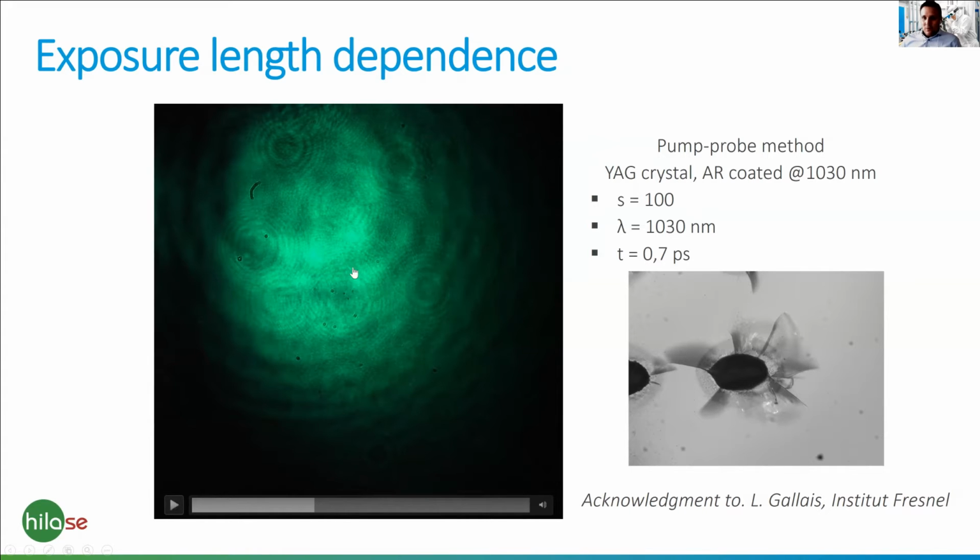At a certain moment, the system of electron recombination and excitation over and over again, releasing the energy into the lattice, eventually leads to the creation of damage precursors, small absorption centers, which keep growing when more pulses are incoming to the interaction.